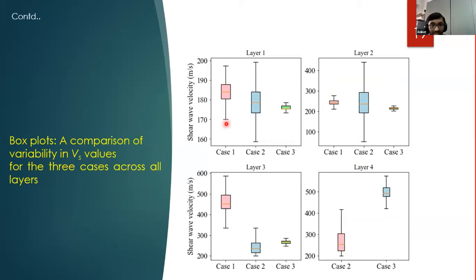For case 1, we can see that VS is varying from around 170 to around 200 meter per second. For case 2, the variability is even higher. But in case 3, when the borehole information is available, the VS value is varying from around 175 to 180 meter per second. That is a significant decrease in variability compared to the previous 2 cases.